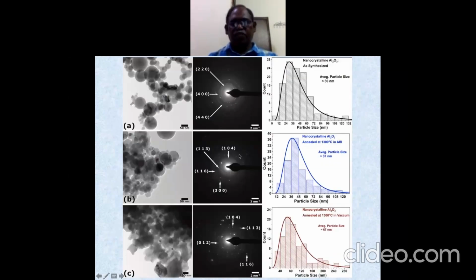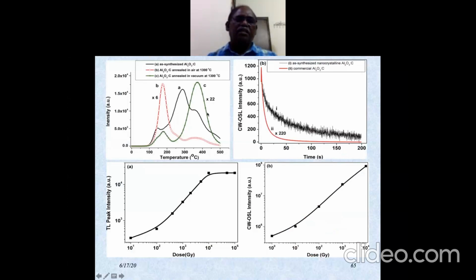The size is maybe around 30 to 37 nanometer. And when we synthesize, it was in the gamma phase, and when you anneal at high temperature, it goes to the alpha phase, and because of the phase change there is always a change in the crystal structure. Generally this material is used in the alpha phase, so there is no problem. Once you achieve that phase at very high temperature and quench it, it is frozen, so not much problem. And we have also seen these OSL decay curves and this dose response, and you can see that you can measure up to 10⁴ gray over here using this.